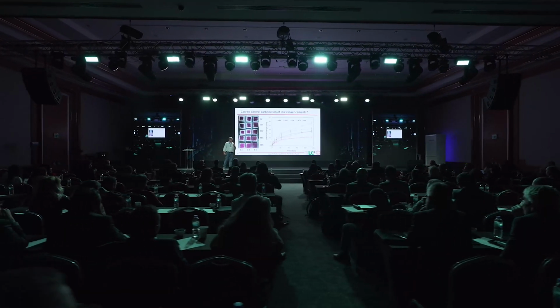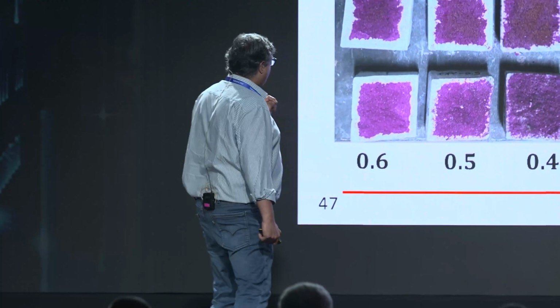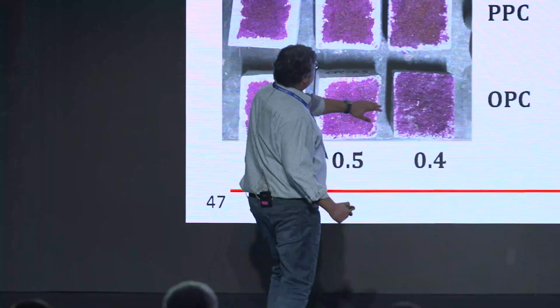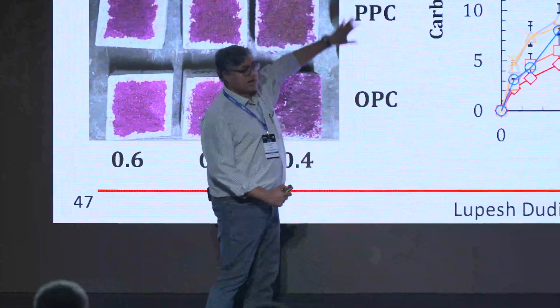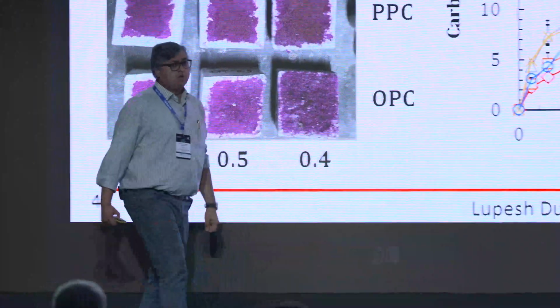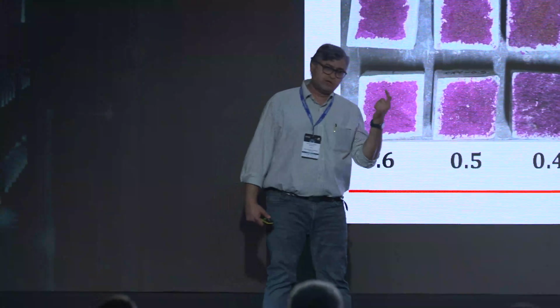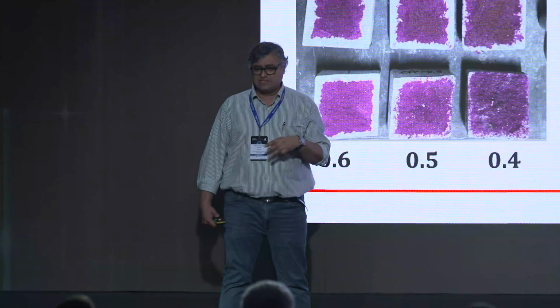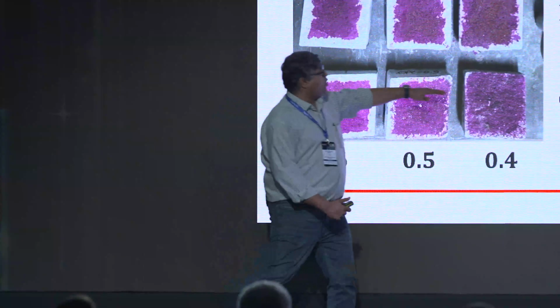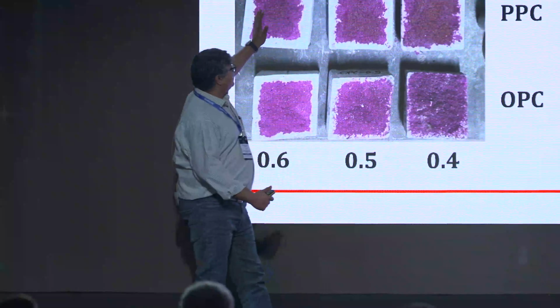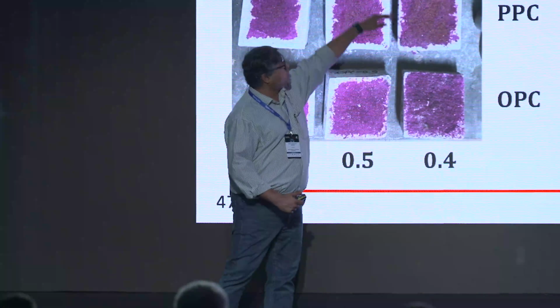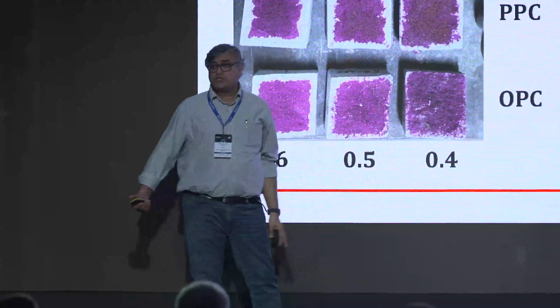Where do you need to take special care? It's carbonation. I'm not saying you should be worried about it or you should stop using LC3 or any low clinker cement. The thing is, whenever you move from a higher clinker content towards a lower clinker content, like you are in this scale over there, whether you're using fly ash-based cement or slag-based cement or a composite cement or LC3, whatever, the moment you reduce the clinker content, carbonation depth in your concrete is going to increase.